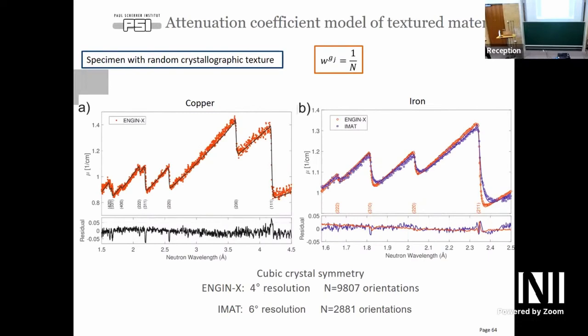So it's the shape at the bottom of the corner due to the instrument? Exactly. Different here in the tails, let's call it. The shape of the edges is linked to the instrumental resolution function. And this model in particular, since we are using that scheme, it would completely follow that. And the top is pretty much the same. But for the models that I showed you before, we have no consideration about that. So this is the first model in which we are including by definition the experimental part of the data.